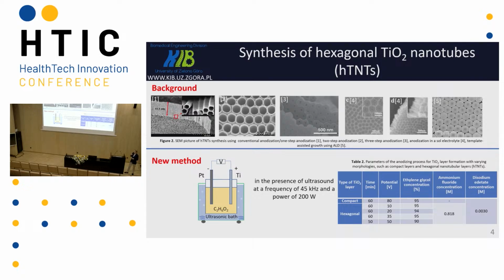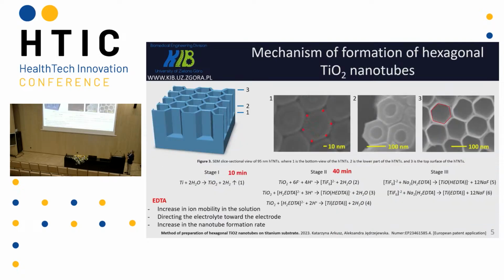So we used the chelating agent, and finally we obtained the hexagonal titanium nanotubes. In this SEM picture, you can see the bottom view of these nanotubes. In this picture, there's a cross-section of hexagonal titanium nanotubes, and here you can see the top view. So generally, the mechanism of formation is very simple. Now I can say it's very simple. It consists of dissolution of titanium using fluoride ion, and the chelating agent, EDTA, increases the dissolution process, resulting in disappearing the spaces between nanotubes.